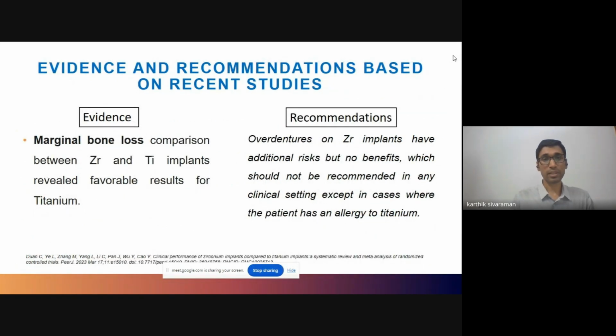Now, what is this other evidence? There was a marginal bone loss comparison between zirconia and titanium implants, and it revealed a favorable result for titanium. Now, this is a bit incomplete because they stated that overall titanium and zirconia performed similar in terms of marginal bone loss, but when they included a study done by Ostman et al. in 2014, including overdentures, the zirconia implants did not fare well.